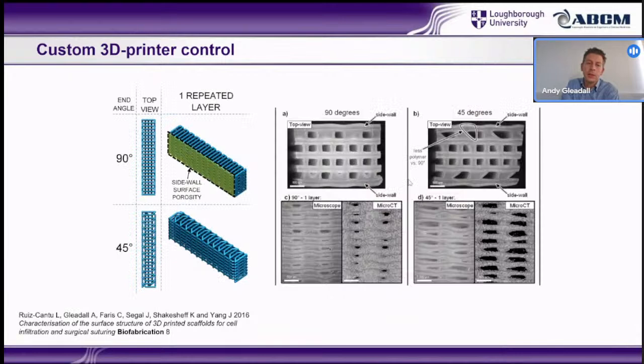And we then took that to design a structure where we wanted porosity in the side walls, which is quite difficult to get. Instead of using the conventional approach of going to the wall, turning 90 degrees and then turning 90 degrees and coming back, we came back at an angle of 45 degrees, which cleared out all this space. Again, it's just a tiny change, but the actual side wall surface is incomparable between those two, because it's just thinking about what we want and what toolpath is actually good for what we're intending to get. So that's the kind of thing that comes when you can design the print path exactly how you want.